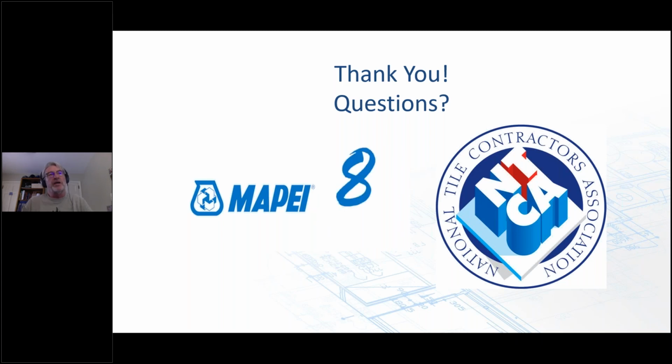So Logan, what you just said is absolutely correct. Definitely your substrate prep is the most important part of your installation. Have a nice flat floor. I don't want to say level, but a flat floor that you're going to work on. Manufacturers have recommendations on how thick a thin set could go. Our industry does. And the reason for that is it shrinks. And if it's got a really good bond to the tile, it can actually crack the tile. Or if the bond isn't that great, it will release from the tile and give you a loose tile or hollow sounding tile and create a problem down the line. It's not made for leveling for sure, thin set.